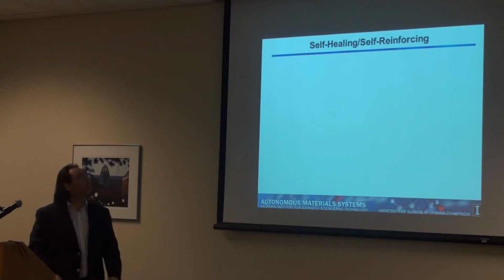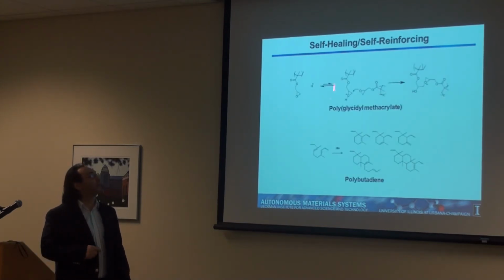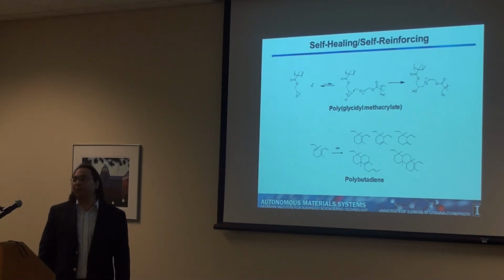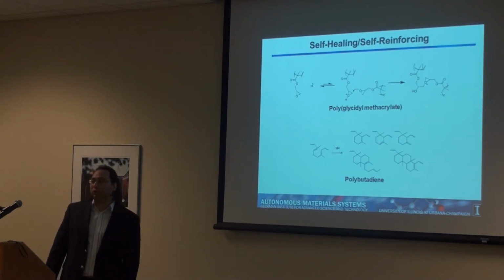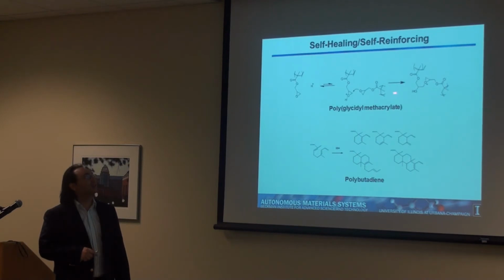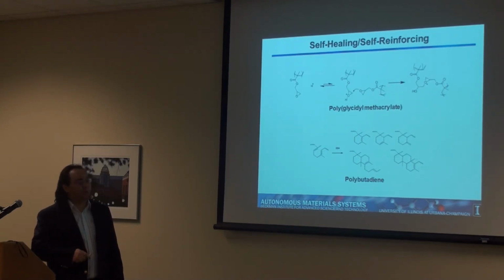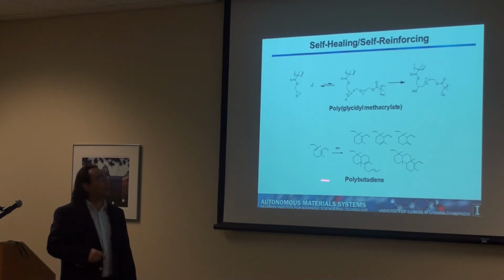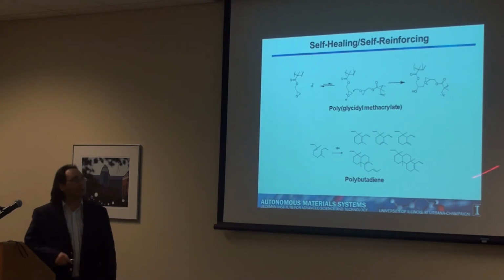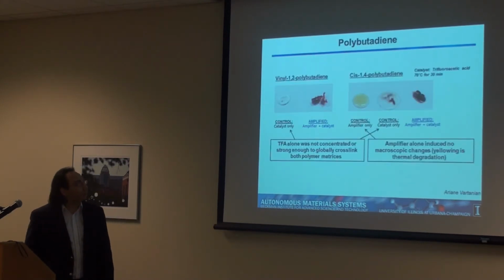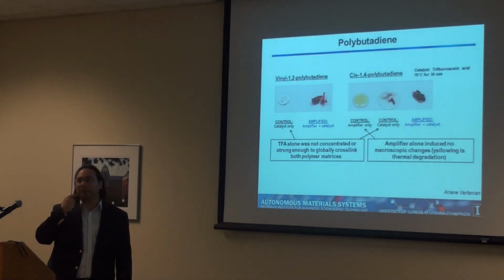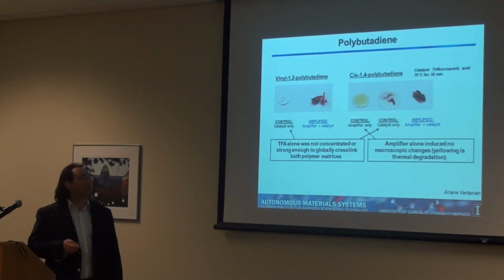Just to give a little bit about the systems that we are working on, the self-healing, so in this case the other type of photoresist. Glycidyl methacrylates are commonly used as photoresists, and you have acid catalyzed cross-linking through these epoxide opening reactions. And polybutadiene undergoes a cyclization reaction in the presence of acid. This one is going quite well. So basically we need an acid amplifier because the acid we produce is not enough.